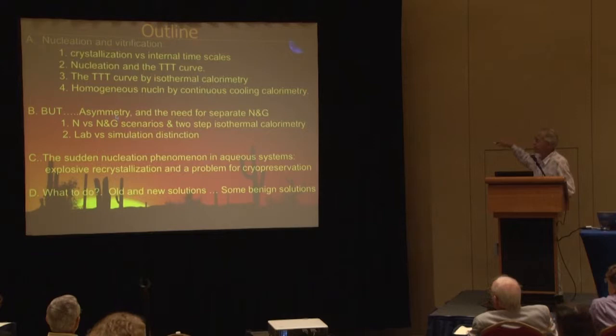And that's all very well, but that requires us then to recognize that what we're determining here is not just nucleation, but some combination of nucleation and growth. And so there's an asymmetry which we've heard a lot about. It's much easier to make a glass than to get back to the liquid without crystallization. And that comes from the fact that nucleation and nucleation plus growth are separable in time.